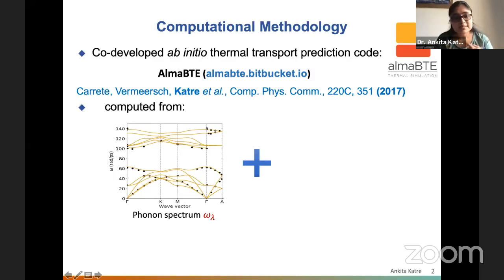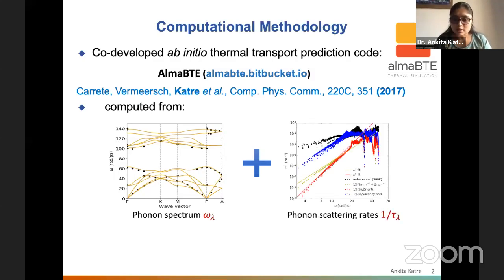Along with that, we need information about how these phonons, these normal modes, are scattered in the lattice. If we don't have any scattering in the lattice, the thermal conductivity is infinite, which we know is not the case practically. In each material there is phonon scattering, which brings that hypothetically infinite limit to a finite thermal conductivity. So we need the information from the harmonic vibrations, the normal modes, and the phonon scattering as well.